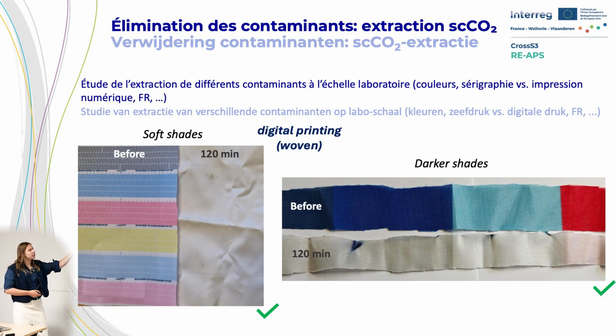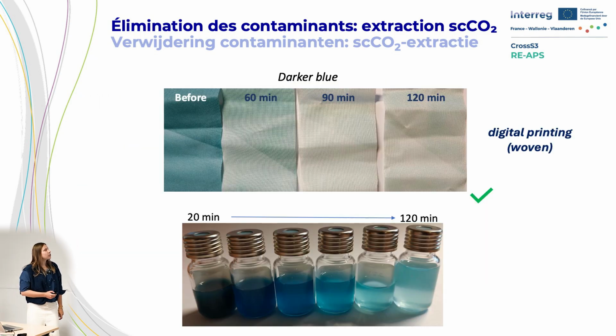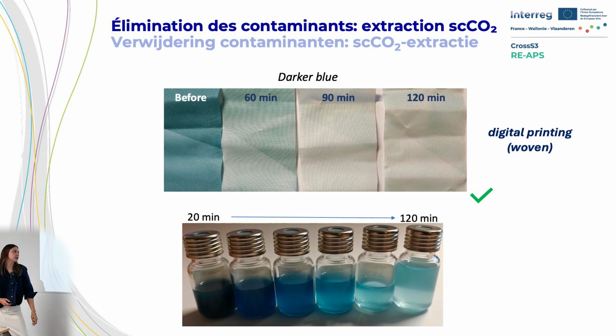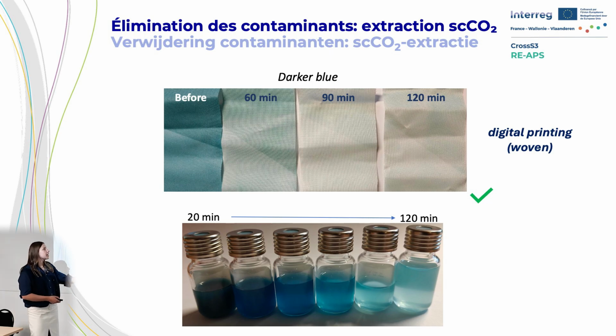Here you see a digitally printed woven textile, in both soft shades and dark shades. It's not very well visible, but both had their color quite well removed. So it was successful. Then we also did the same type of material, a digitally printed woven textile, but this time with a darker blue color. Here you can see the result after different times in the supercritical CO2 extraction. After 60 minutes the color was already partly removed, but not completely. After 90 minutes it was a lot better, and after 2 hours as well.